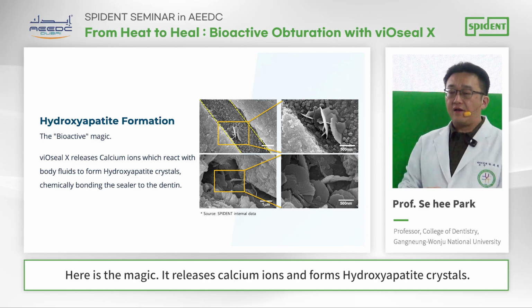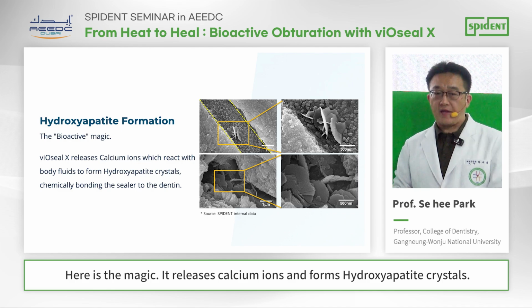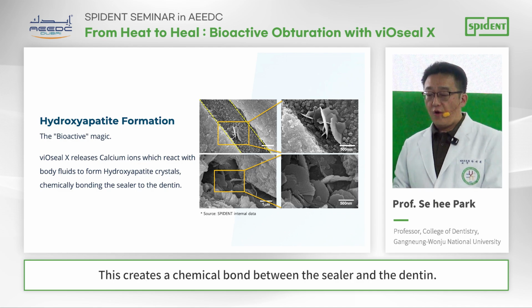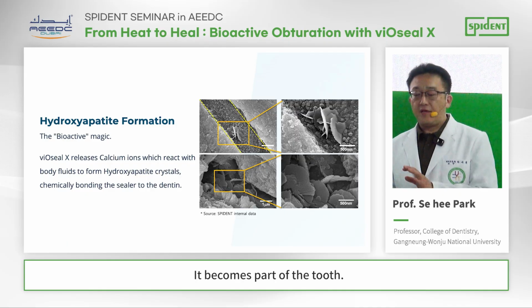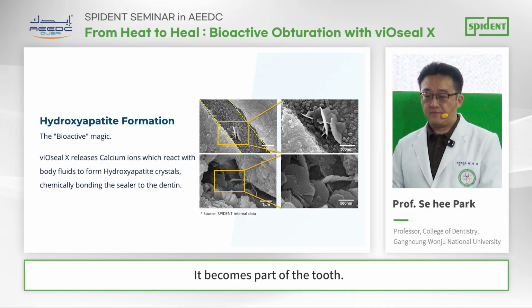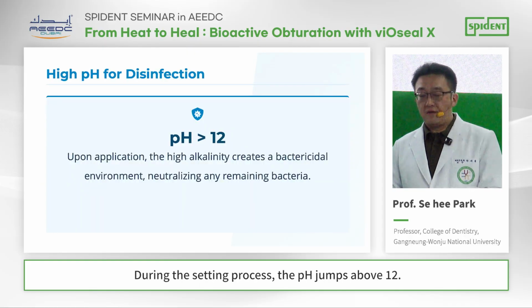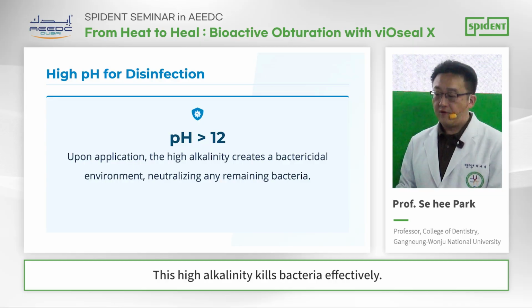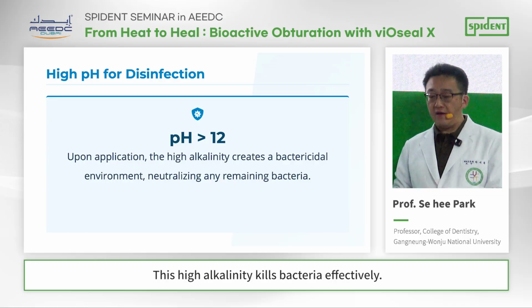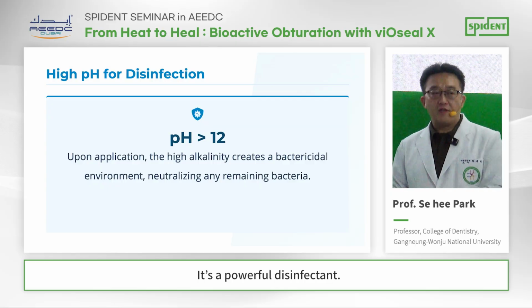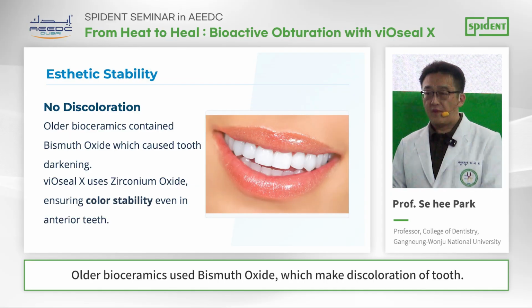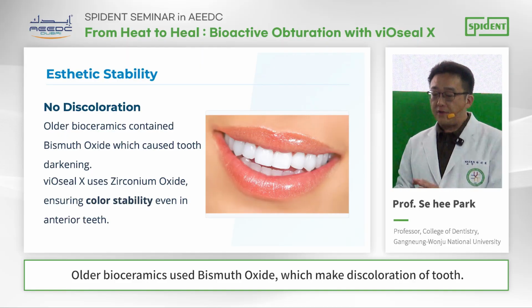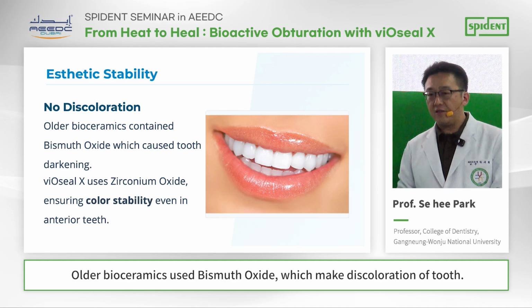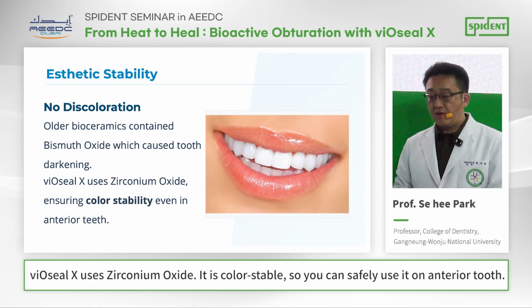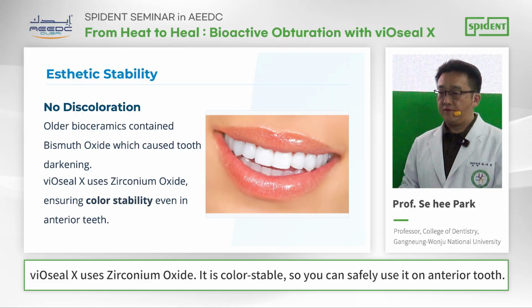Here is the magic. It releases calcium ions and forms hydroxyapatite. This creates a chemical bond between the sealer and the dentin, and it becomes part of the tooth. During the setting process, the pH jumps above 12. The higher alkalinity kills bacteria effectively. It's a powerful disinfectant. Other bioceramic sealers use bismuth oxide, which causes discoloration of the tooth, but viOseal X uses zirconium oxide. It is color stable, so you can safely use it in an anterior tooth.